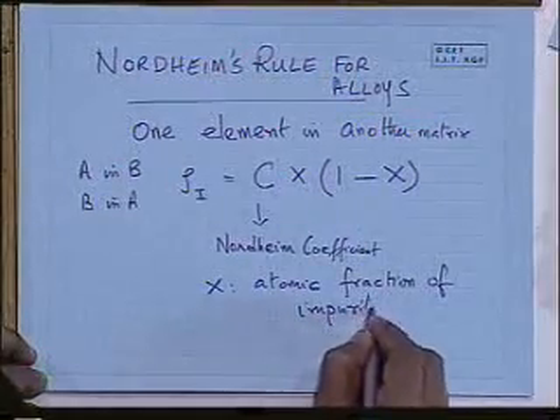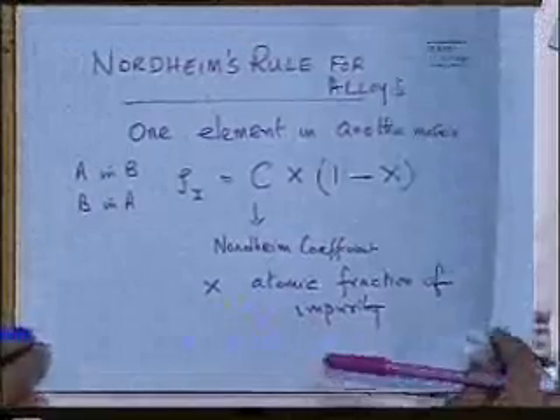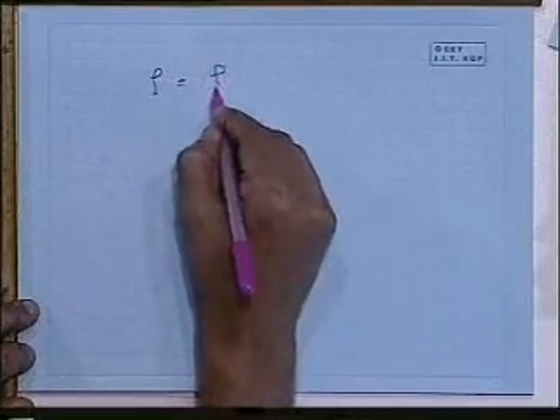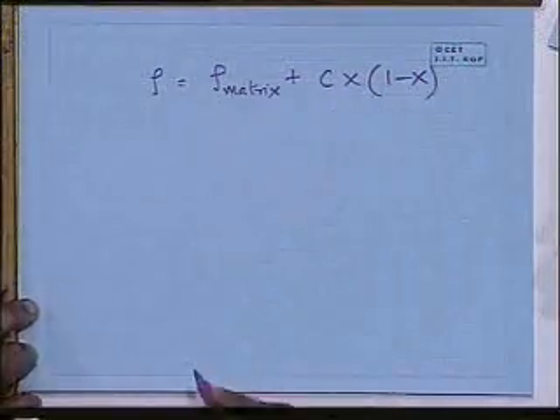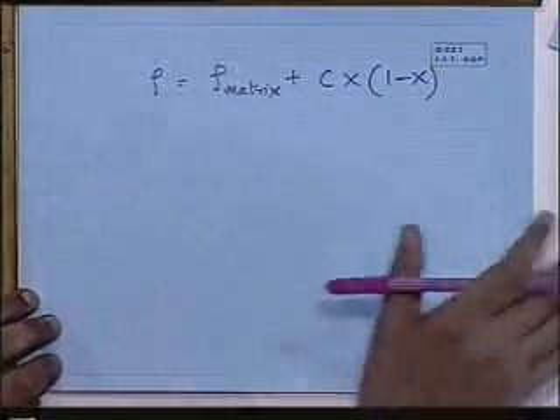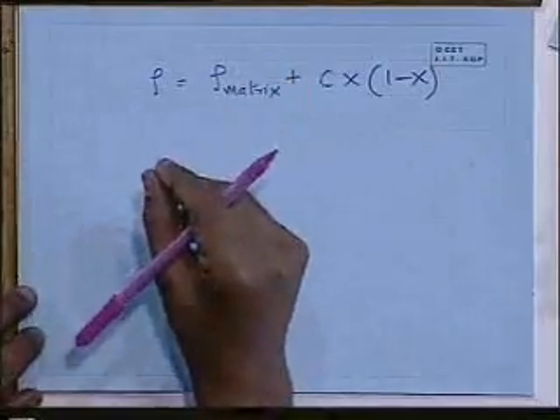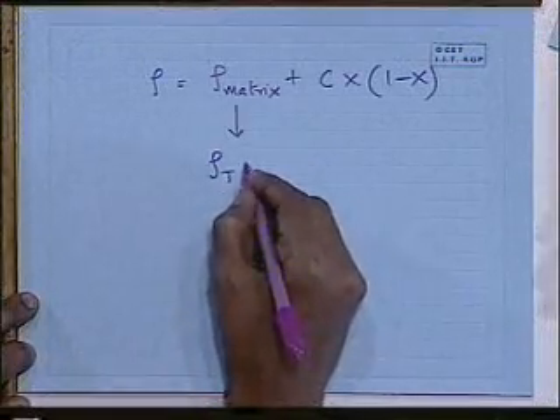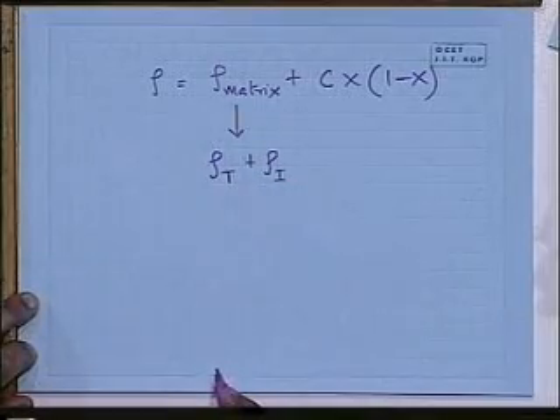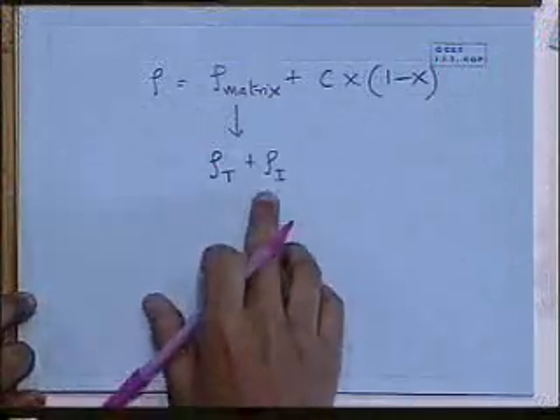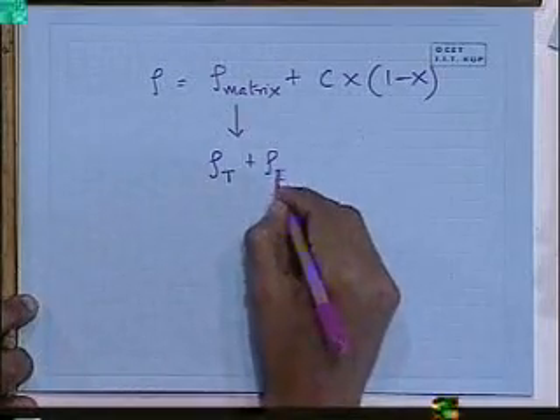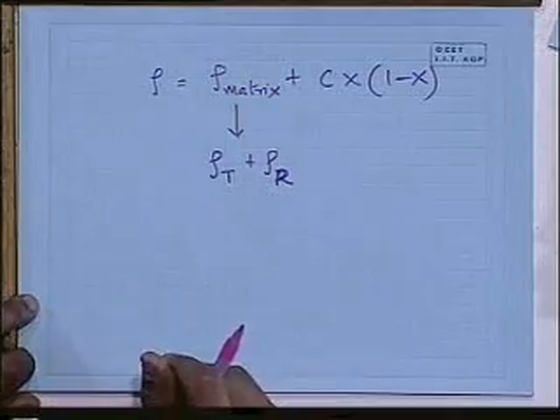All right. So here we can have rho I is equal to C x (1 minus x). Now the total resistivity then is rho matrix plus C x (1 minus x). The matrix itself, in the absence of this impurity, has got a certain resistivity, and what Nordheim said is that part of it is the additional term that is added on to the matrix. The matrix itself consists of the temperature dependent phonon scattering plus impurity scattering term for the matrix itself. There may be other defects and so on that add up here. And then you've got what we called the residual scattering earlier. And then you have this term that is being added on by the deliberate alloying.